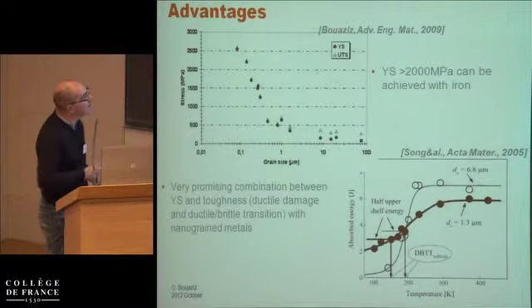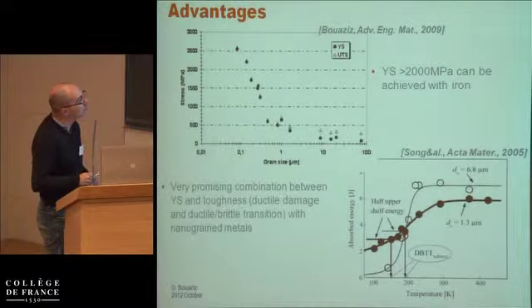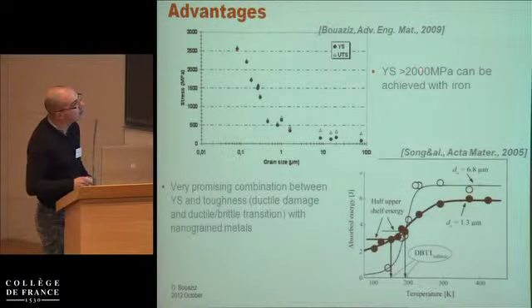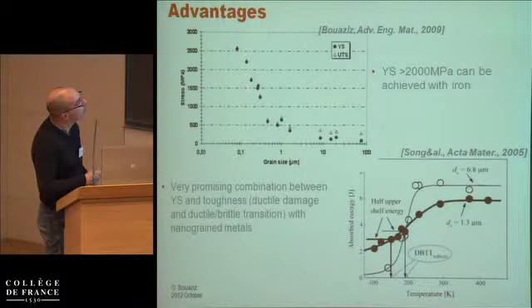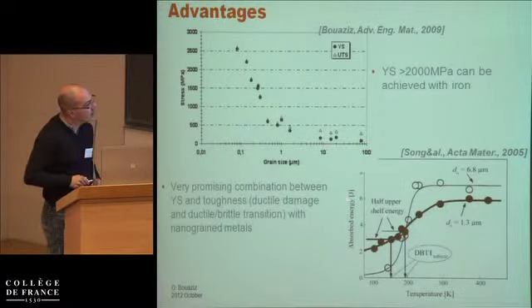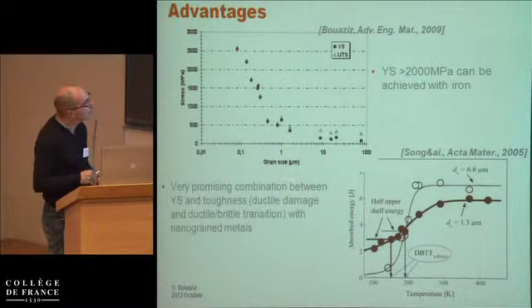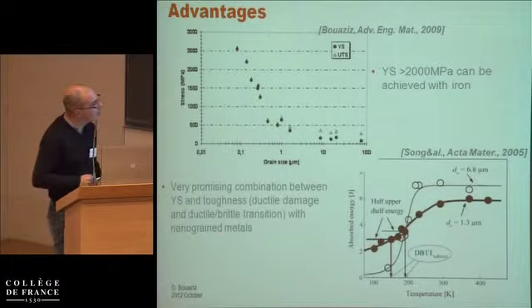This technique allows a grain size in the nanometer scale. For iron, for instance, you can achieve a yield strength higher than 2 GPa, especially in the domain of grain sizes between 100 nanometers and 10 nanometers. In addition, an interest has been shown in the decrease of the ductile-brittle transition temperature. So it is a very promising combination between yield strength and toughness with nanograin metals.